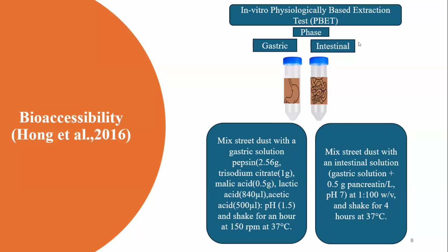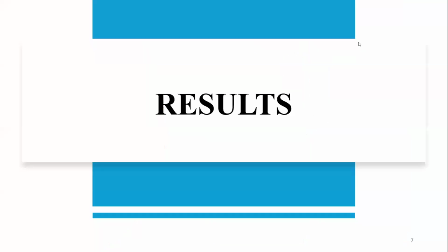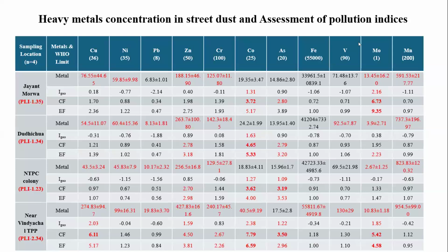Then again, we mix the dust with 0.5 gram of pancreatin and bile salt. Then again, we shake it for 4 hours at 37 degrees Celsius, followed by analysis of the sample in ICP-OES. Then for results and discussion, we see the heavy metal concentration in street dust and assessment of pollution indices.